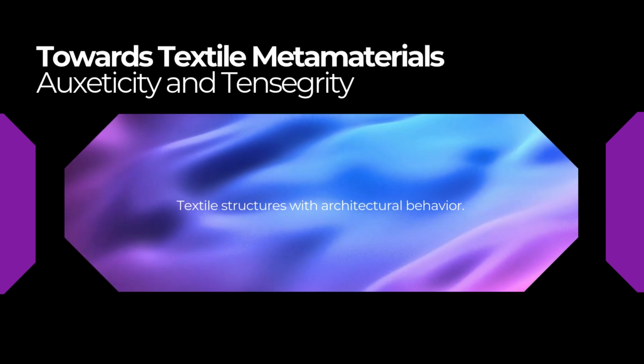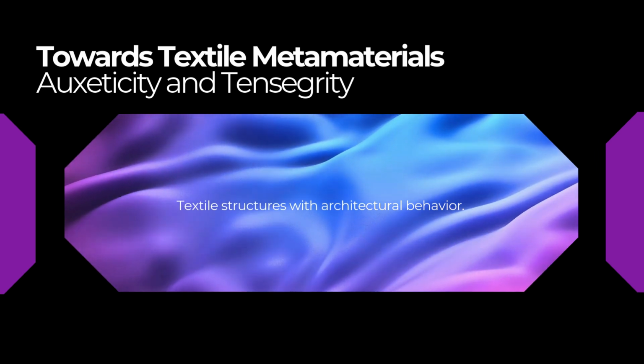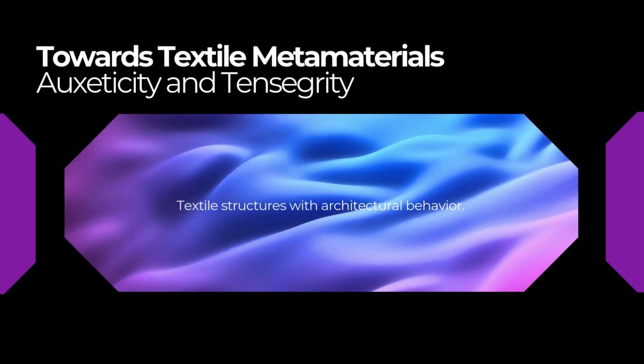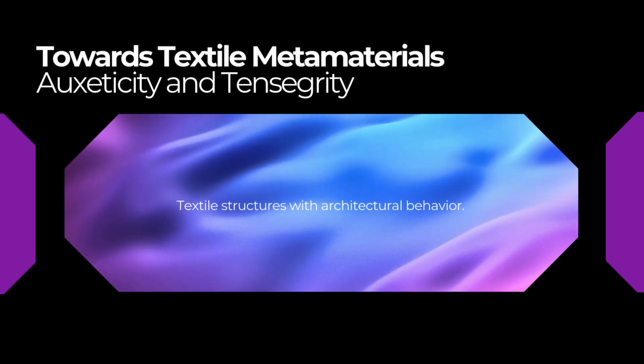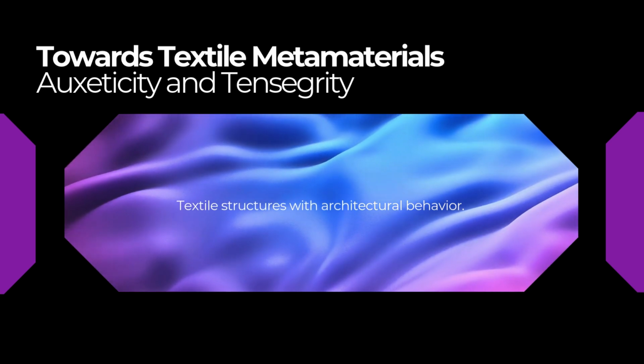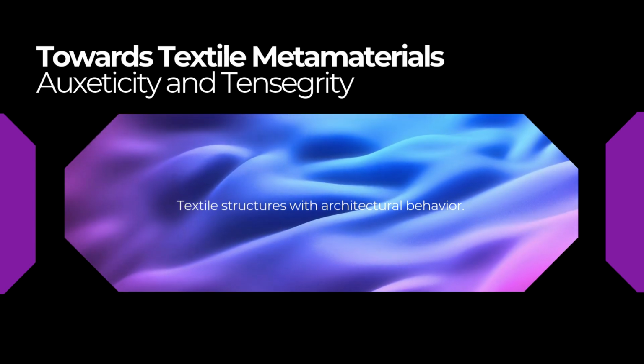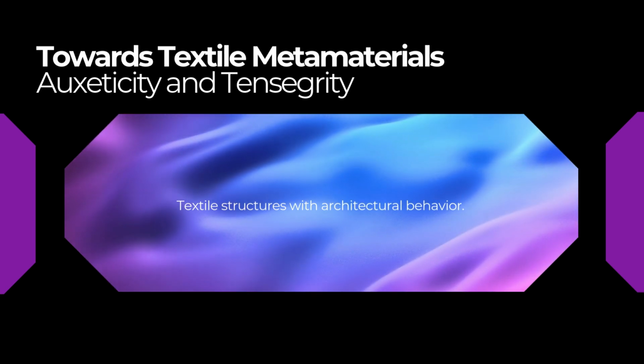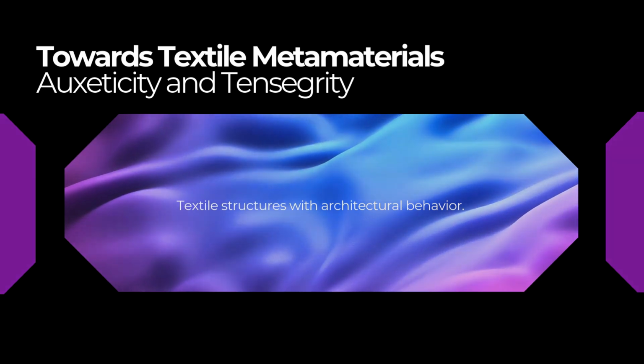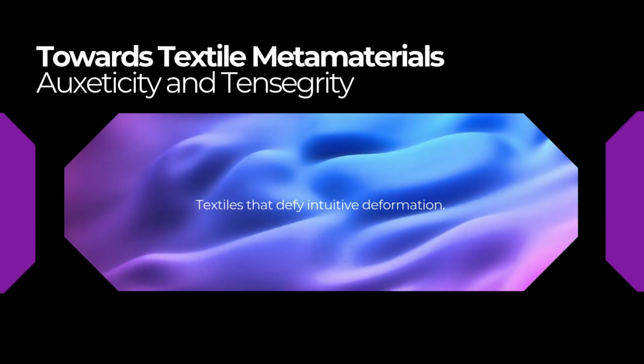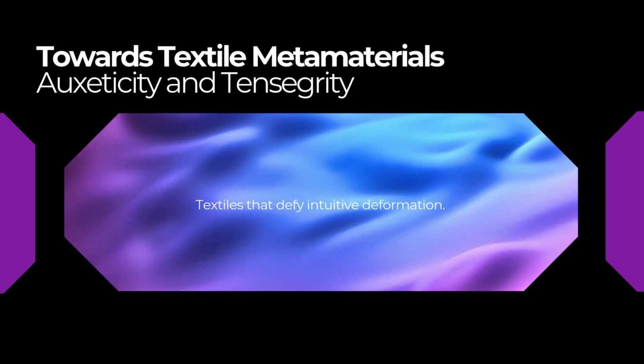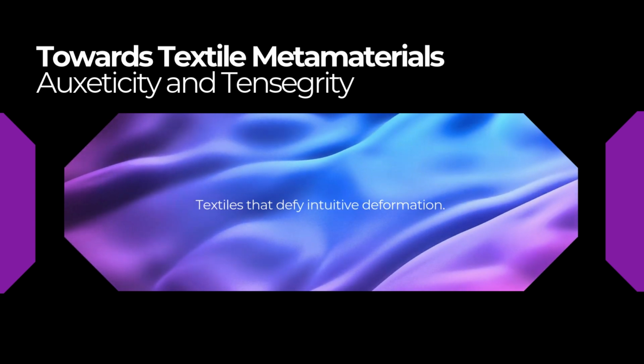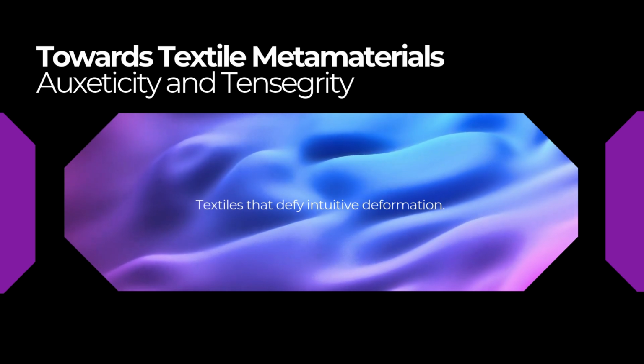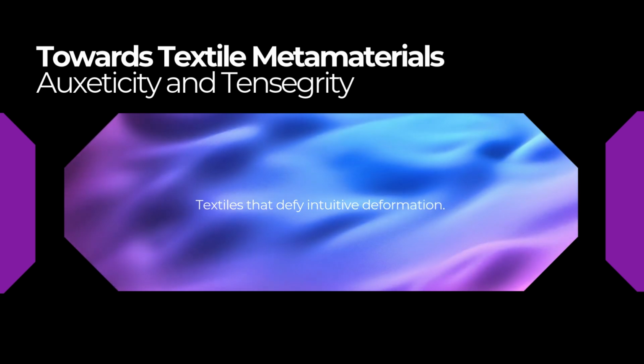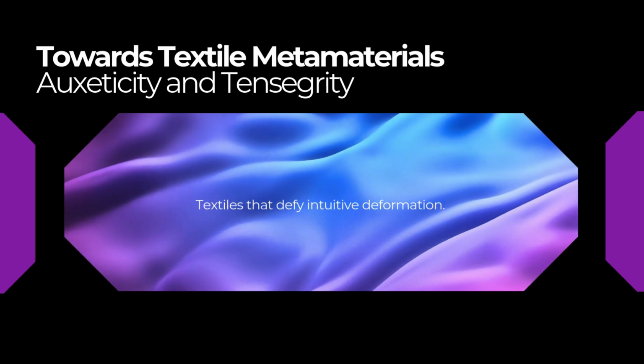It starts with the material's structural permanence. Yes. What's fascinating is what happened when they let it relax after that intense compression. Compared to similar PET nonwovens or even wool felts, the TR felt showed the lowest thickness recovery. So it didn't bounce back as much. Not even close. It only bounced back to about 45% of its original thickness after the pressure was removed. This is a huge indicator that the treatment worked. It created a highly stable, highly bonded, dense structure. They locked the network in place.